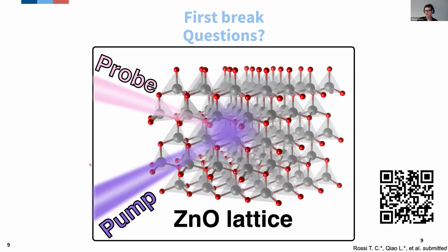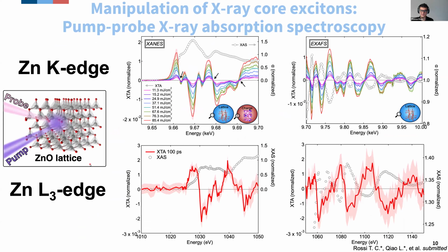Okay, thanks. All right, so I'm showing here how raw data typically look. Two experiments, one at the zinc K edge and one at the zinc L3 edge. We did the measurements at multiple fluences because we try to understand the scaling of the effect we are observing with the amount of carriers that we have generated in our semiconductor.